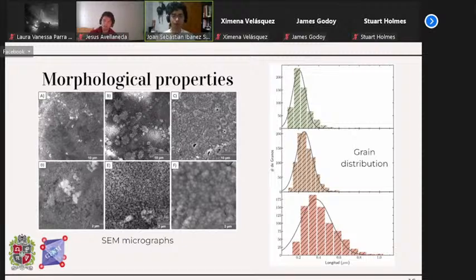In particular, it is worth mentioning that in the first sintering, the grains of what seemed to be the majority phase were sometimes too small to distinguish. That is, you can see some white dots that are not entirely well defined. After the second sintering, those white dots began to grow to form the nucleation process that we expected from the solid-state reaction. And after the last sintering process, in which we jumped from 900 degrees Celsius up to 1100 degrees Celsius, we found that basically we had a majority phase. The color was very homogeneous, and so we thought that we had completed our process.